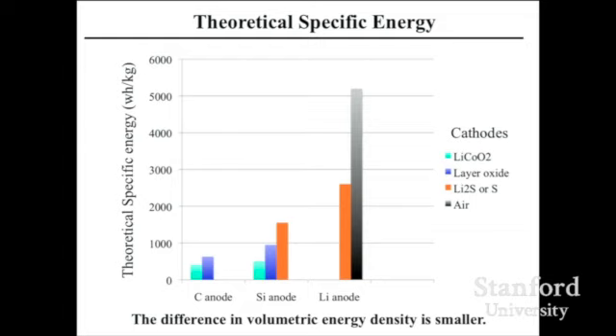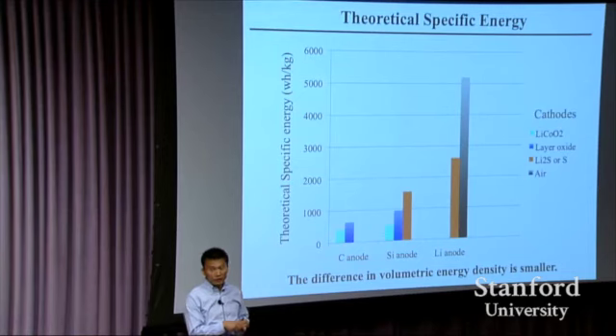But if you can make these materials work, this is a plot of energy per unit weight versus different anodes. Color indicates different cathodes right here. This is a theoretical one, only considering active materials weight. For current lithium-ion battery technology, you divide this number roughly by half. That's the real cell energy density you're talking about. So carbon with a lithium cobalt oxide, this is used in your cell phone. So you're talking about roughly getting close to 180, 200 in reality. Theoretical is about 400 also.